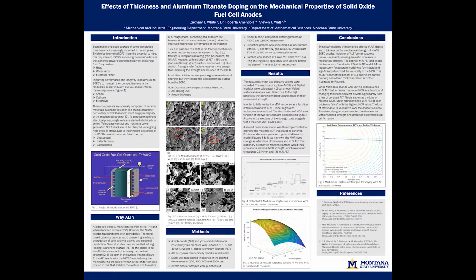Figure 3 shows how the fracture mechanism changes with the inclusion of ALT. In panel B, the fracture is intergranular, meaning that crack propagation follows along the grain boundaries. However, inclusion of ALT above 5% leads to transgranular fracture, in which cracks propagate through the grains. This can be distinguished by the flat, faceted nature of the surface in panels C and D, as opposed to B, which is relatively rough. This is important because more energy is required for transgranular fracture, thus increasing the mechanical strength.